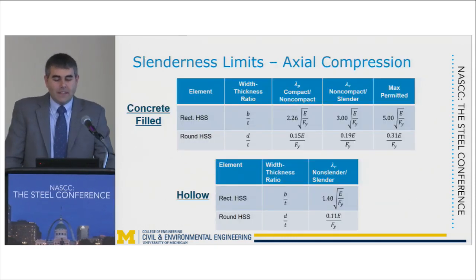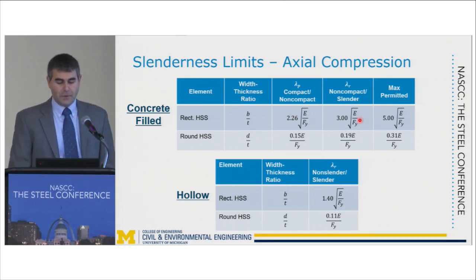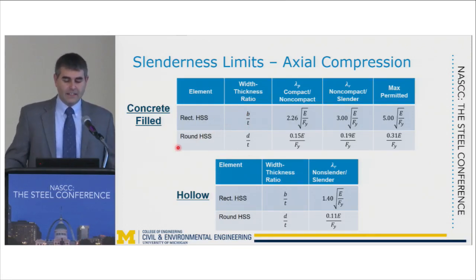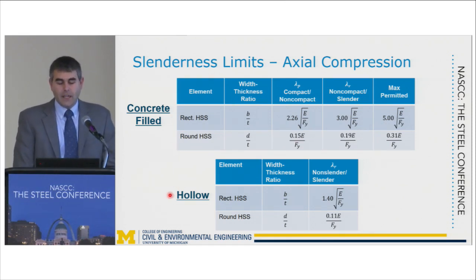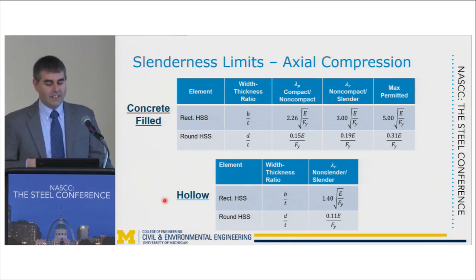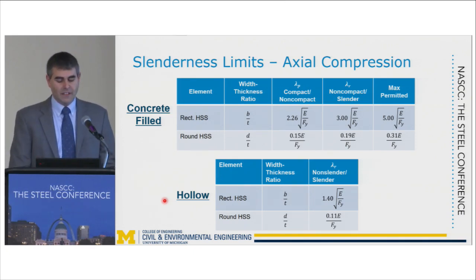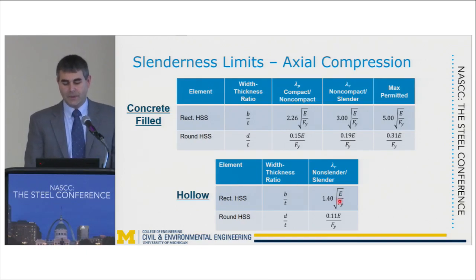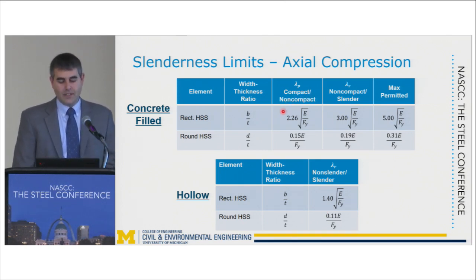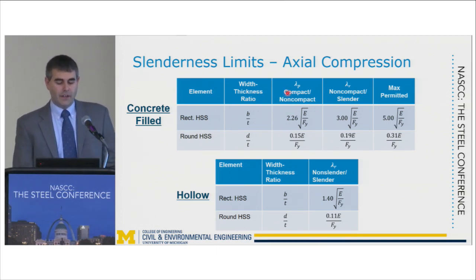So if we look at how we're going to classify the sections, we can first consider axial compression, and you can see the compact, non-compact, and slender limits for concrete-filled sections up here for rectangular, where you're looking at the minimum width-thickness ratio, and for round HSS, where you're looking at the depth-to-thickness ratio. I included in the bottom table the same equations for hollow sections, where for axial compression you're looking at the boundary between non-slender and slender. And here you can really see the advantage. The equation for a hollow section is 1.4 times the square root of E over Fy, whereas the boundary between compact and non-compact for concrete-filled jumps up to 2.26 times the square root of E over Fy. So you have a little more to play with there with the concrete-filled sections.